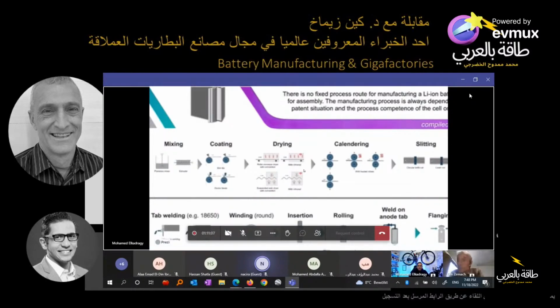And this is where science becomes super important. So you think, okay, so I've got this wet slurry, I've coated it on this thing, it's got a bunch of binder glue in it, I just need to evaporate off the water in my anode, and then it'll all be stuck together. And the answer is, yeah, that's true. If you dry it too fast, though, what happens is, think of having this layer of wet electrode goo on your foil. And as you're evaporating it, it's only evaporating from the top surface, right? It's not evaporating through the foil.